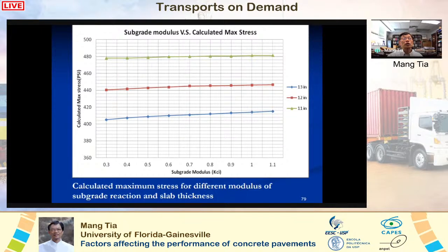This figure shows plots of maximum stress versus modulus of subgrade reaction for different slab thickness from the critical stress analysis. It can be seen that when the slab thickness is 11 inch or higher, increasing the subgrade modulus actually increases the maximum stress in the concrete slab when we calculate the stress using the critical loading condition.